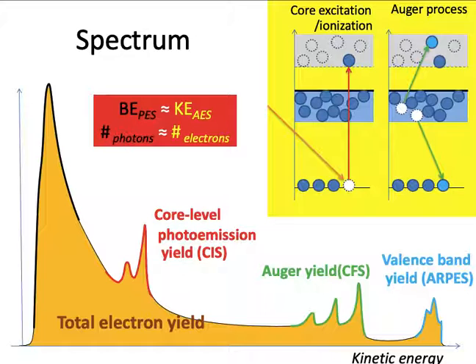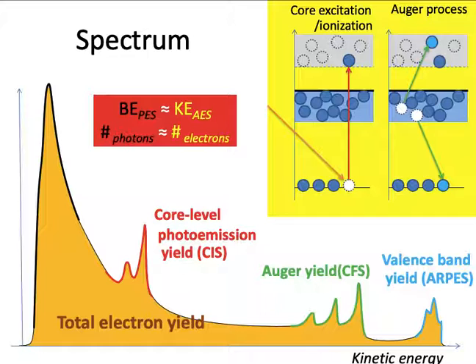This is a survey scan of the XPS spectrum. You may see Auger peaks in XPS, because these depend on the relaxation process after the ionization of an electron. If you have multiple atomic elements in your sample, Auger peaks may overlap with XPS peaks, so you must carefully choose the appropriate photon energy for your sample. You may also see a large background effect at lower kinetic energies in the spectrum, so you must carefully choose the appropriate background shape before peak analysis.